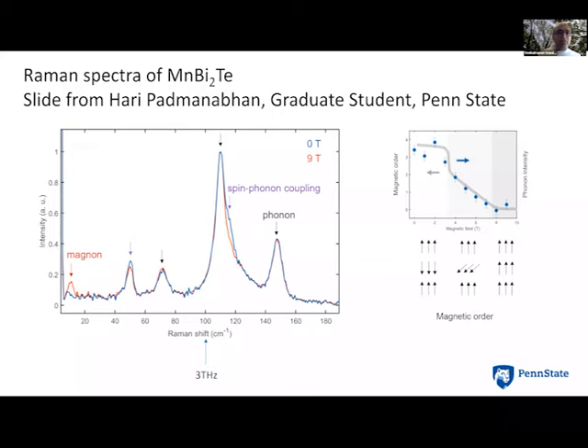The interesting thing I want to point out is some of the subtleties. There is also magnetism you can pick out from here. The blue and the red are at 0 Tesla versus 9 Tesla. You see how there's a little shoulder where it says spin phonon coupling. There's a little shoulder. And then there is a peak in the red that comes up at the very low end, around 10 wave numbers. Those are magnons. Those are spin waves that are dancing around, and they are also influencing the lattice vibrations.